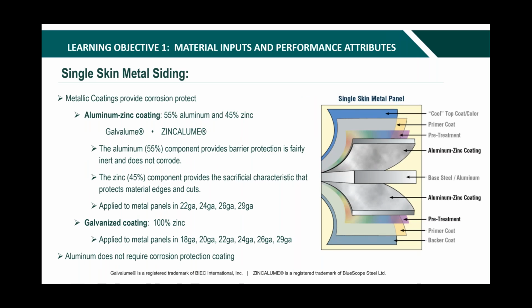Metallic coatings provide corrosion protection. The aluminum zinc coating is comprised of 55% aluminum and 45% zinc. Galvalume and Zincalume are both registered trademark names. The aluminum component provides barrier protection, and it's fairly inert and does not corrode. The zinc, which is 45%, provides the sacrificial characteristic that protects the material edges and cuts. This coating is applied to metal panels in 22 gauge, 24, 26, and 29.